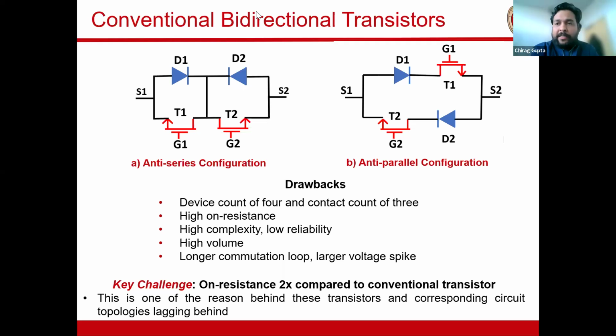Another reason is beyond the complexity. If we get rid of the complexity, the other part you can see is that there is a good chance you'll get some resistance penalty. You'll have at least 2x the amount of resistance of a conventional transistor for the same rated voltage. For example, for a 600 volt, if you have a 10 ohm part, if you take two transistors, you might have 20 ohm or even larger. And this is again not ideal, because in order to get the bidirectional blocking capability, we are paying that extra resistance penalty. And for all these reasons, in my opinion, they don't make it a very attractive solution.